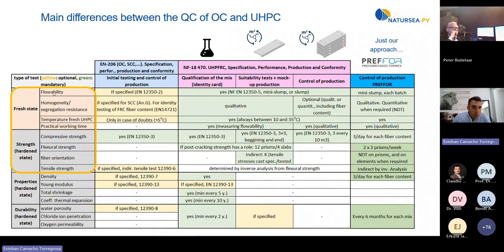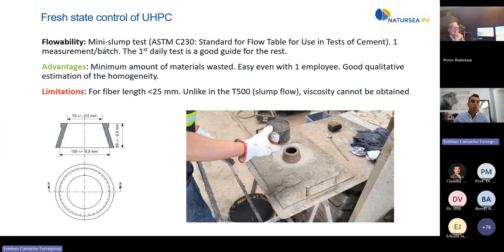Here we are going to cover mainly the fresh state and the hardened state. The first thing I am going to speak about is how we control flowability. Following the French norm, we need to control the flowability of all of our batches, and we also do this. We use the mini slump test. I think it's quite common in UHPC, because the typical slump flow test consumes too much material, and it's more tricky and more complex.